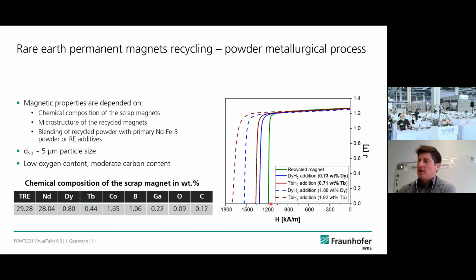And of course, like shown here, with recycled powder in green and with optimized magnets in blue and red, a blending can also occur during the processing. So in this case, we added heavy rare earth hydrides for increasing coercivity. So it's pretty easy to meet specification even with recycled products from end-of-life magnets when this material is blended and is produced like magnets from elements.